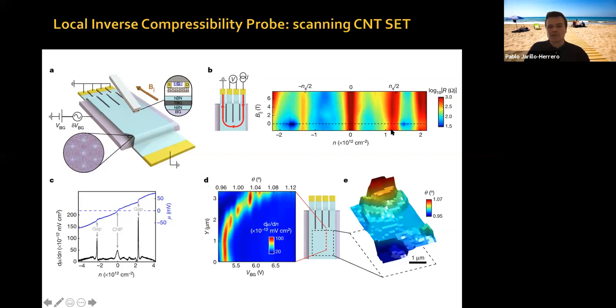And you have these superconducting domes for electrons and for holes, okay? So not a great device, but good enough for what we did. And the nice thing in particular is that because he has this scanning SET, and it's a very small device, he can go along the device and measure what the twist angle is. The presence of this band insulator tells you the twist angle.